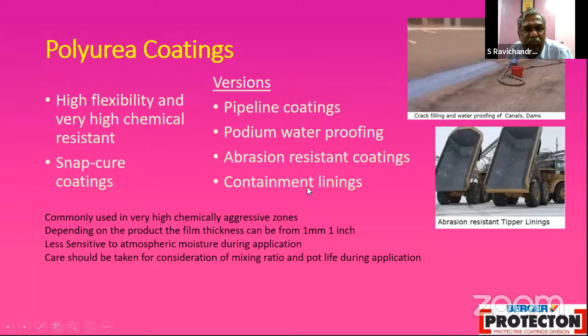Polyurea is a new development. These are all called snap cure coatings. By the time you mix the two components of the paint, it would have set in 15 to 20 seconds. It sets off very fast. These coatings are used to ensure you do not have any leakages, or it can take higher abrasion. So in open canals and conduits, this can be applied. It requires high temperature, around 70 degrees, to be heated during spray application. It's a very costly product, but still fantastic usage.